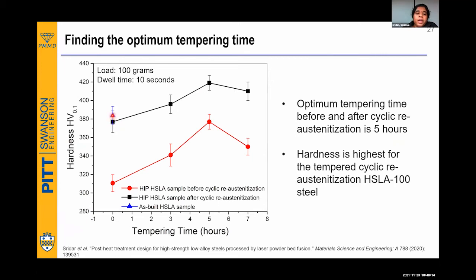But one more good news: what we can see is that the hardness of the as-built material and the HIP HSLA with cyclic reaustenization is more or less pretty close, which means we have improved the... I would not, that's an overpromise. I would just say we have improved the hardness. But hardness is not always the indicator of achieving good mechanical properties,